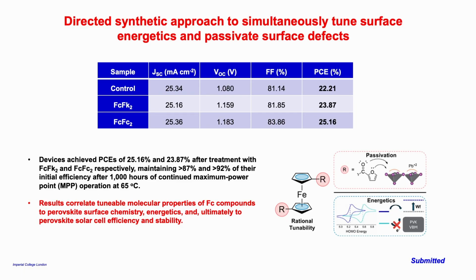Okay, so here is the slide that summarizes this. So basically, on the right-hand side, again, you can see very good efficiencies for this area, around sort of 24, 25%. But the key thing now is we're understanding more about our materials. We can actually begin to tune whether we have an electron-deficient compound, whether it matches the conduction band of our device, whether it matches the valence band of our device. Can we push the materials up and below that?